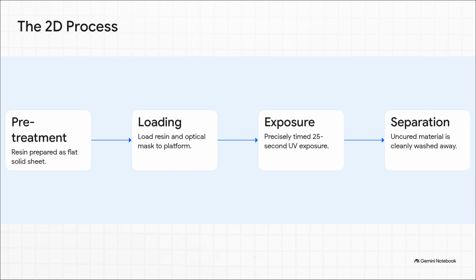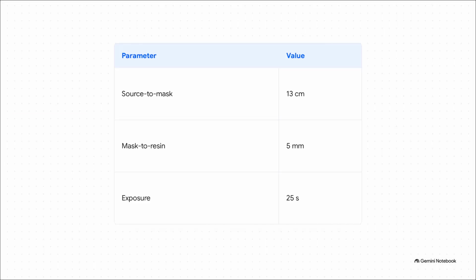There's no messy recoating cycle, no waiting around for liquid to level out. The platform just steps, exposes, and moves on. Of course, getting the system to work perfectly required locking down the exact optical physics. Through a ton of testing, they found the absolute optimal parameters to balance curing completeness and dimensional accuracy. The ideal distance from the UV source to the mask? Exactly 13 centimeters. The gap between the mask and the solid resin? Just 5 millimeters. And the optimal exposure time is exactly 25 seconds.